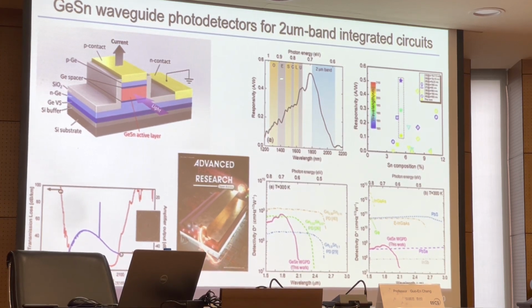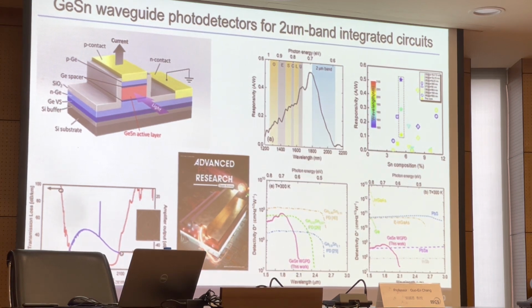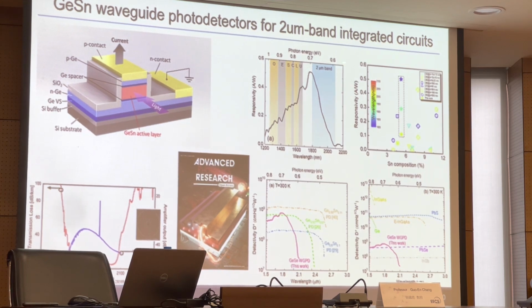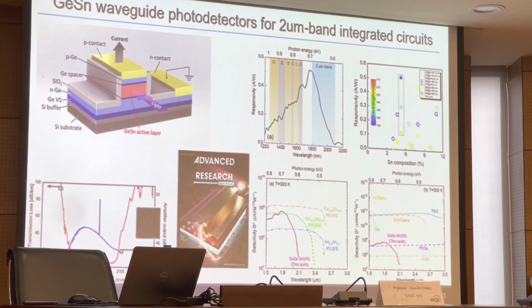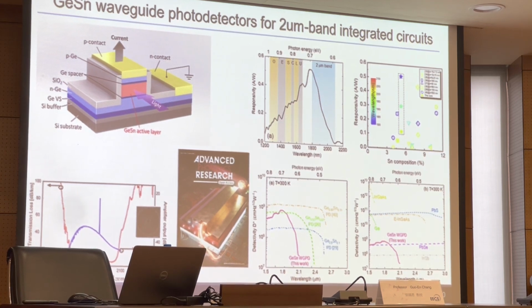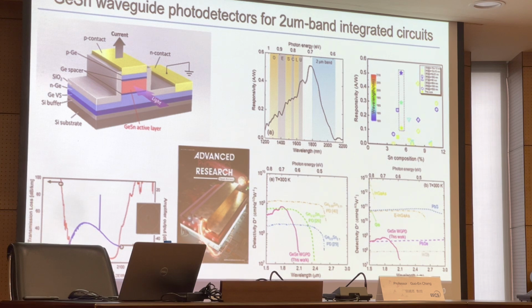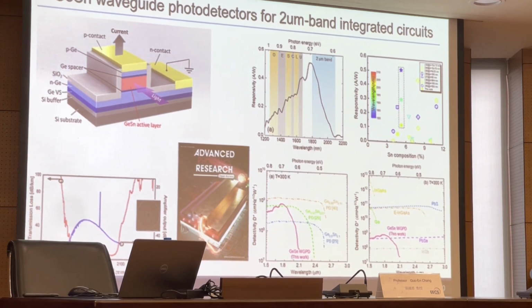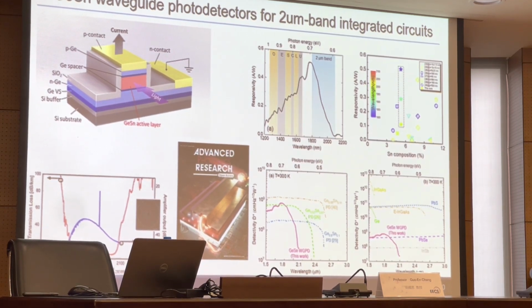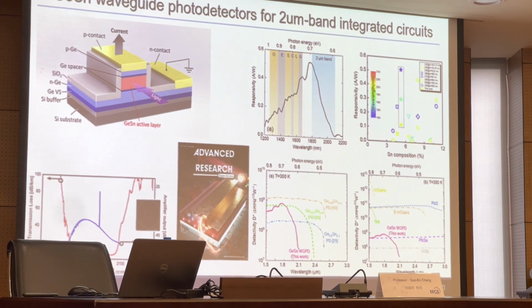So we can extend the photo detection range to about 2000 nanometers, with a cutoff around 2.2 micron. We can cover the entire telecommunication band, and also cover one of the new emerging 2 micron wavelength bands. This device can be very useful for 2 micron band communication. Our work was selected as the back cover of the journal Advanced Photonics Research.